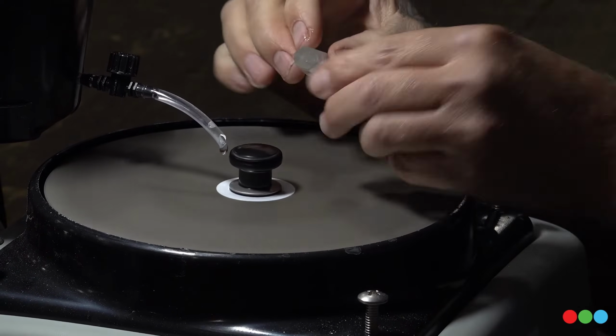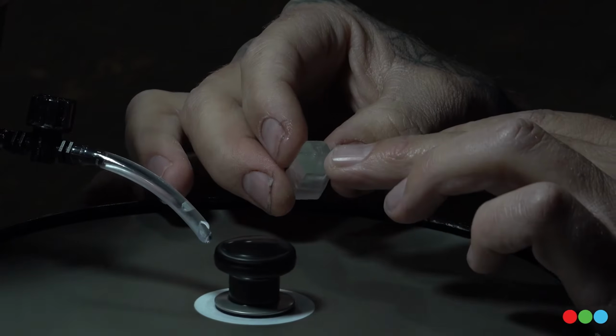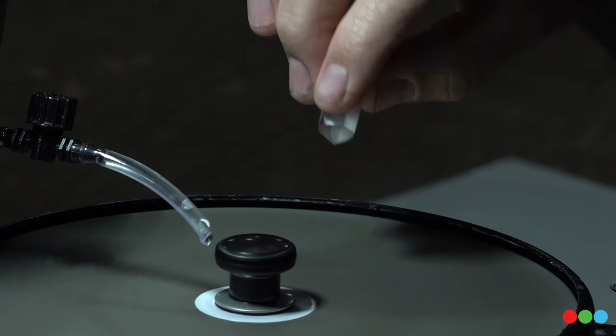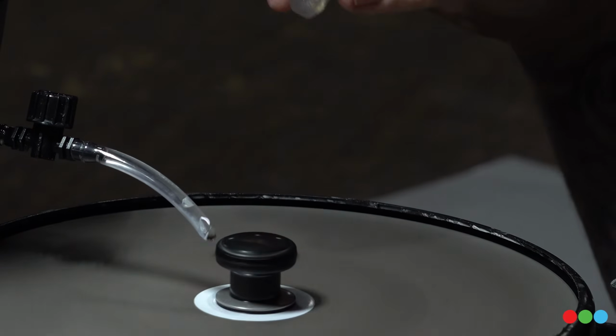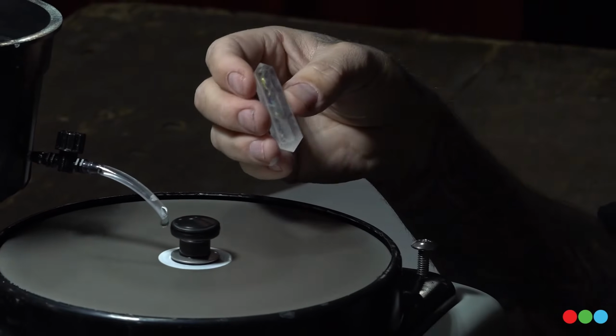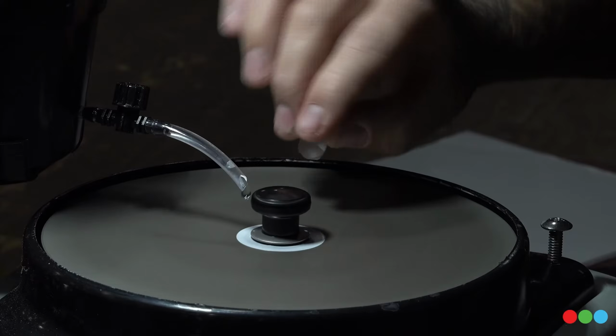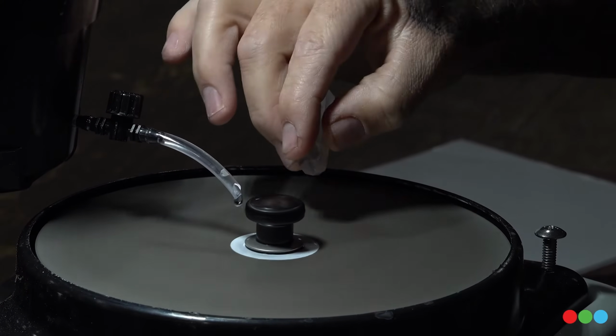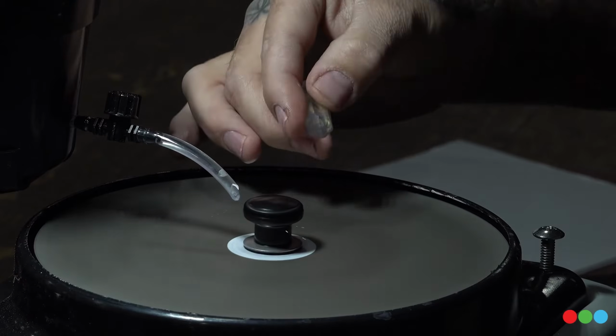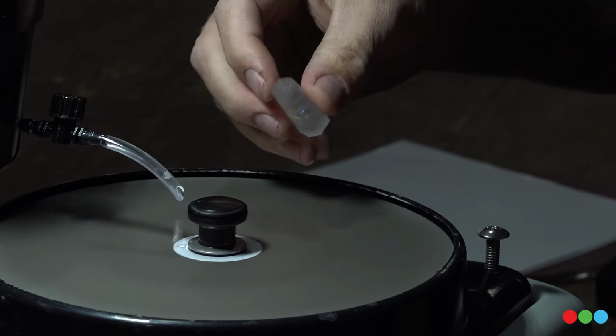I don't know if you can see that in the camera. These lines, some of these lines are going diagonal. And that's all because of how I'm holding it. That's all because of the pressure that I'm putting on there. Like I said, this is much trickier. This might be something I would like to use a finer grit on so that I take less material off. Not so fast, take a little less material off at a time, but that's okay. It's all about the pressure from left to right, that is how your lines are going to end up. If you notice that your lines are going at a certain angle, you can just twist your wrist and go in the opposite direction. And you'll see that line center out, it will center for you.